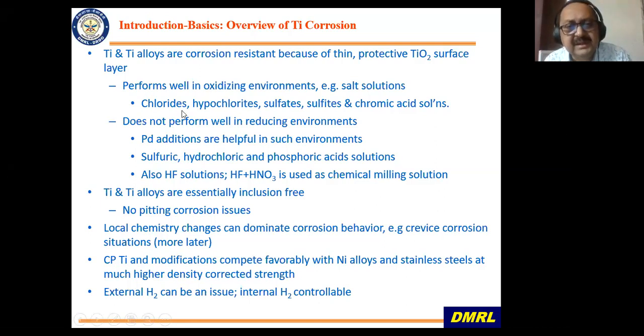Now, this oxide layer performs very well in oxidizing atmospheres or solutions which have chlorides, sulfates, etc. But it does not perform very well in reducing atmospheres like sulfuric acid, and also HF. That is why HF plus HNO3 is what is known as Kroll's reagent. It is used as a common etchant for titanium alloys. Now, the corrosion resistance of titanium can also be enhanced by adding certain elements like palladium. So in electrode materials, palladium is added so that corrosion resistance increases.